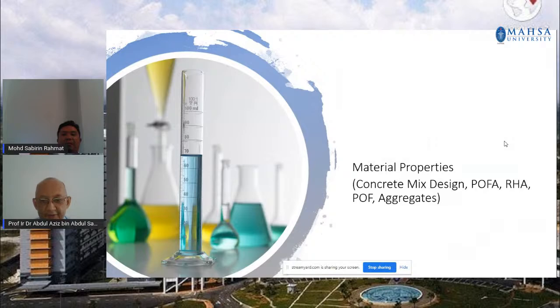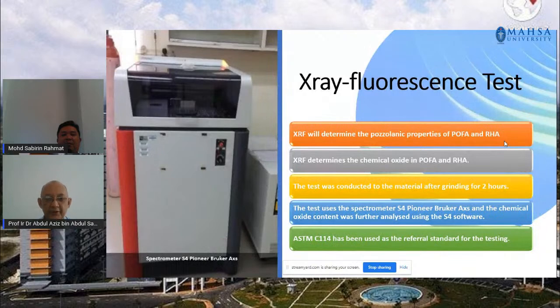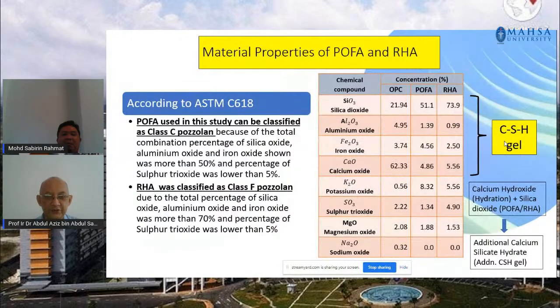Okay, so the material properties. In terms of the palm oil fuel ash and rice-husk ash, we have to do a chemical composition test to make sure that they have sufficient chemical properties to act as a cement replacement, or what we call a pozzolanic material. So this is the machine that we use, the X-ray fluorescent test machine, XRF, was used to determine the chemical properties of both palm oil fuel ash and rice-husk ash. And these are the results that we managed to obtain.